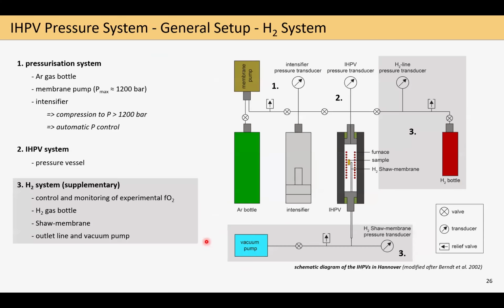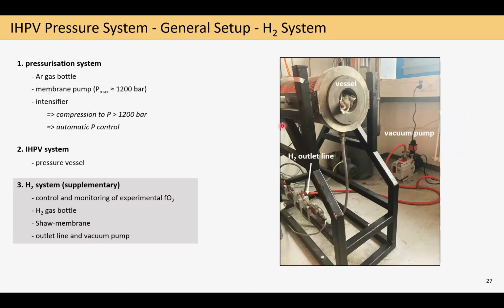And with this, let's now have a look at the so-called hydrogen system, which is, as I said, supplementary, meaning the vessel runs without it, but can be equipped with it. And this mainly serves us to control and also monitor the experimental fO2 conditions, and thereby consists of a hydrogen bottle, which is connected here to the vessel, allowing us to put some hydrogen into the vessel itself, and a Shaw membrane which is located inside of the vessel and then via this outgoing line connected to a pressure transducer and a vacuum pump. And here is an image of one of our vessels which is equipped with this hydrogen system.